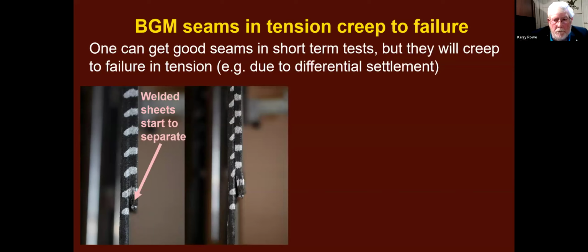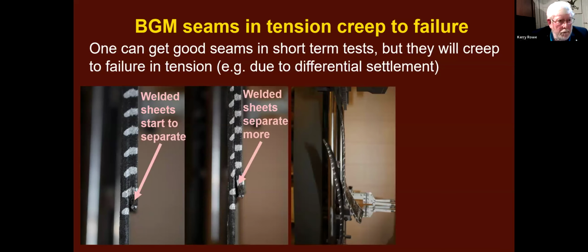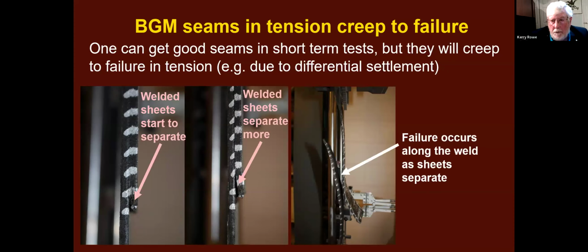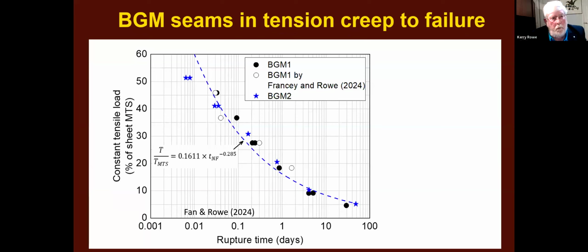Longer, the lines aren't even connected anymore, and it's opening more. And a little time later, it fails. Same story that you just heard about from Eric. So let's quantify this, and we took a different approach, but nevertheless came back with the same or very similar results. We tested 2 different BGMs from 2 different manufacturers, and we subject them to a constant stress as a proportion of the sheet stress.